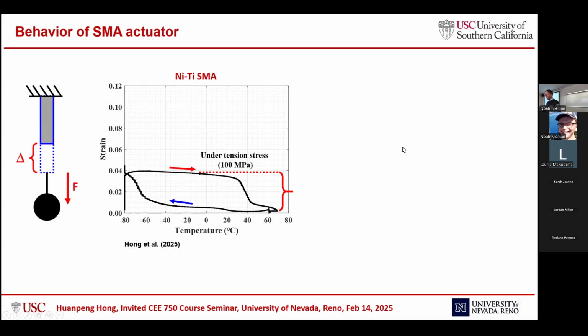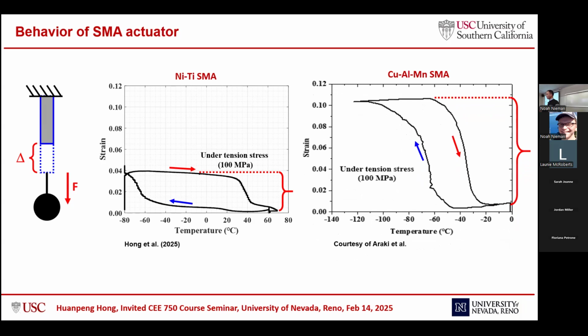So this is good enough. However, for copper aluminum manganese alloy, under the same load of 100 megapascal, this material works from around minus 120 Celsius and ends up at around 0 Celsius. And the impressive thing is that it can generate a stroke of more than 10%. So this is really suitable for space applications.